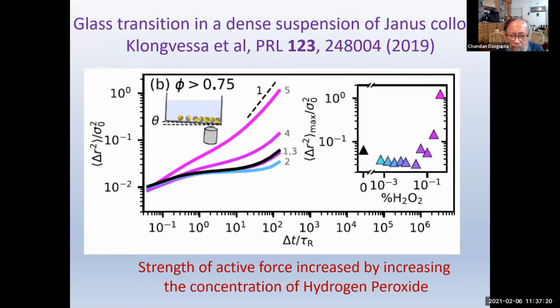We are talking about these Janus colloids, where one side is coated with some metal that, when you put it in hydrogen peroxide, produces some motion by itself, which makes them active or self-propelled. And the strength of the active force can be changed by changing the concentration of hydrogen peroxide. What they get from this experiment is basically mean square displacement versus time. As we go up, the active force is being increased.